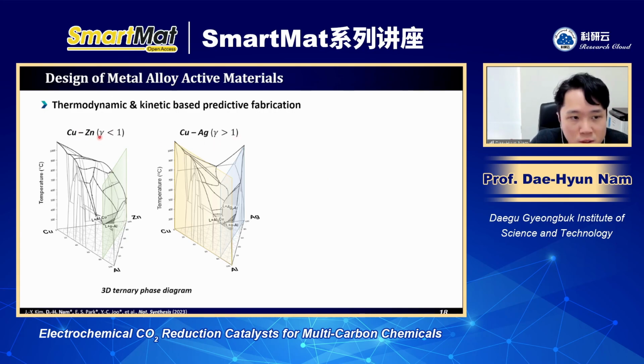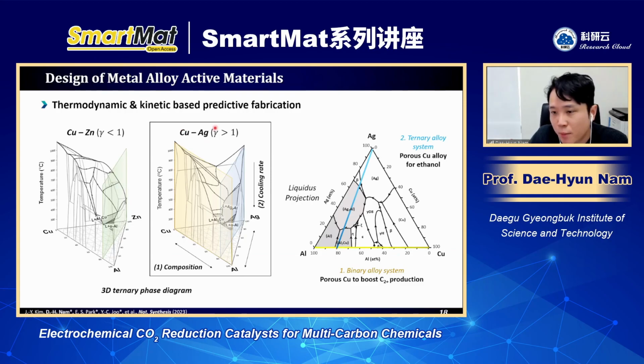activity coefficient. As I mentioned, if the activity coefficient is lower than one, it means copper and zinc are easy to mix. In the case of copper and silver, the activity coefficient is larger than one, it means they are immiscible. So we focus on this copper silver. And as I mentioned, we have to apply a third element to control the interface between copper and silver. We chose aluminum as the third element. Aluminum can mix with copper and silver simultaneously, and it has a higher oxidation tendency than copper and silver. It means aluminum can be selectively leached out when you put this alloy into acid.